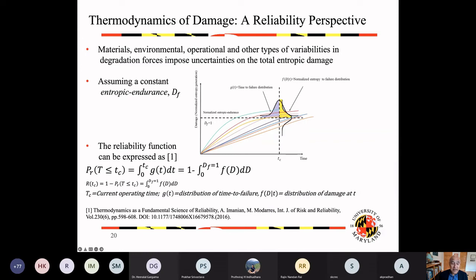I can correlate this F, the failure, the distribution of entropy, and convert them into the distribution of the time of failure, which is G, through this very simple equation that you can see again. I refer you to this journal paper, which described this equation in more detail, but that's how I convert. And I say that the distribution of time of failure is derived, is the key word, is derived, not found from historical data, is derived from a distribution which has foundation in science.